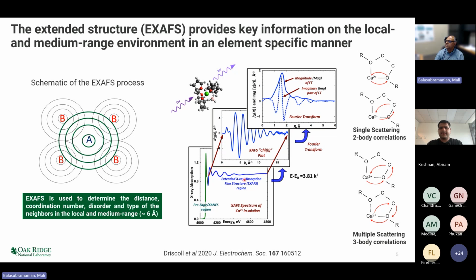You extract these oscillations. It is converted from energy to a wave vector space, and the XAFS exists as a series of sine waves in this wave vector space. One can then Fourier transform these sine waves by established methods and then analyze this data using standard approaches, which has now been well developed to extract structural information.